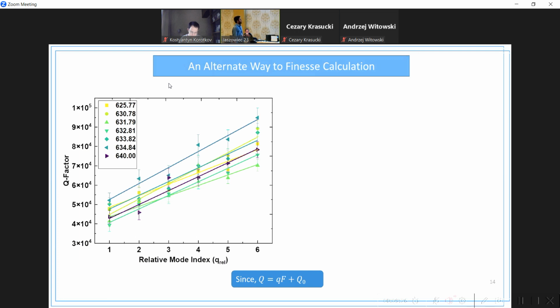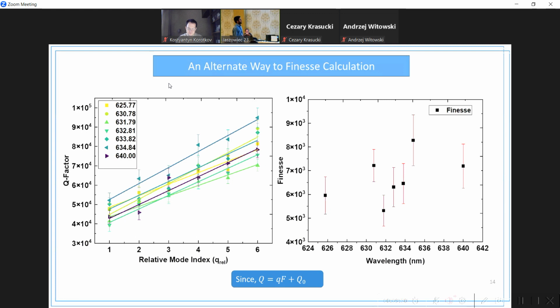By using this information, you can also calculate finesse at this point, which is basically the slope of these lines. Each line corresponds to a different wavelength, and the slope of this line gives us the finesse.